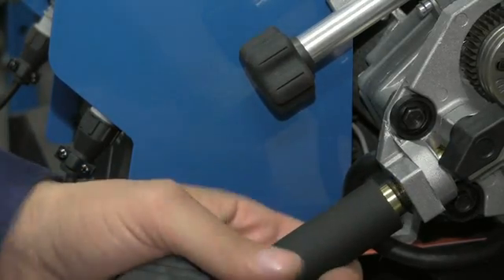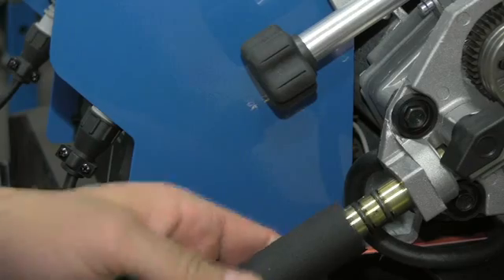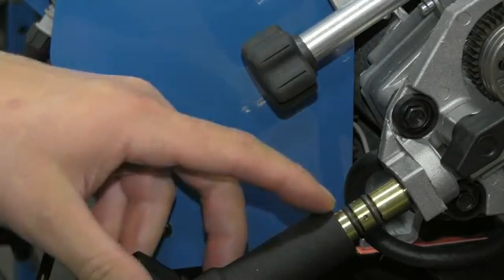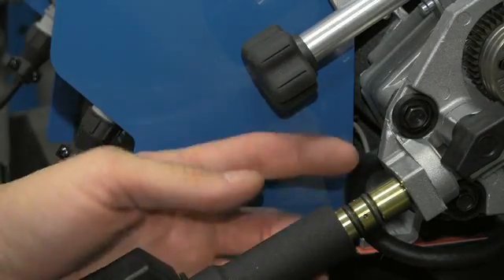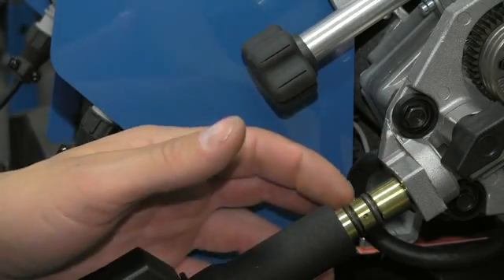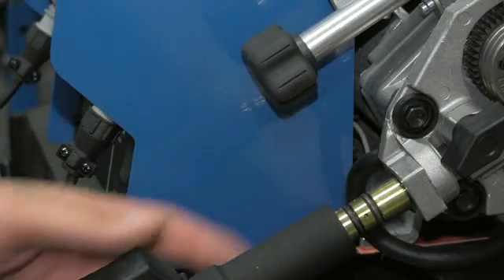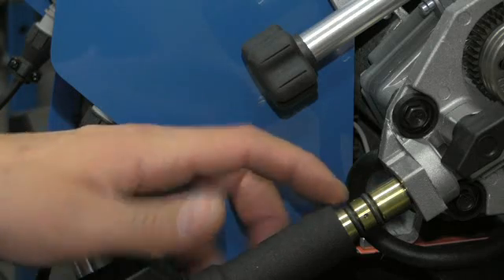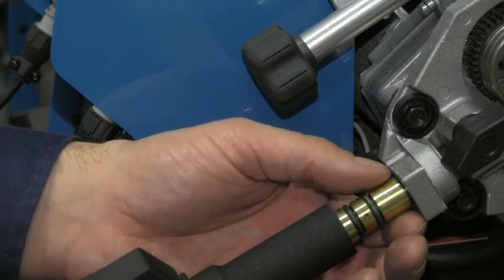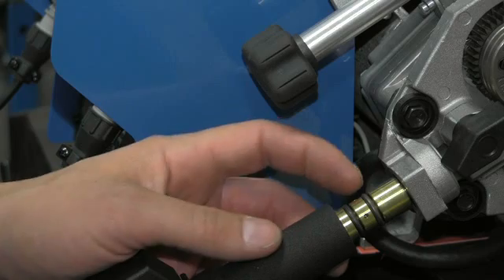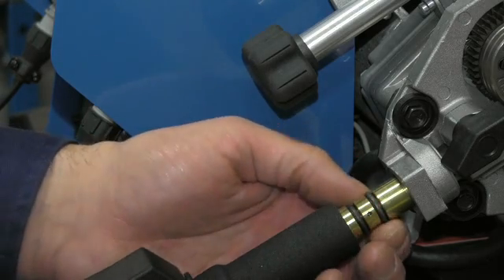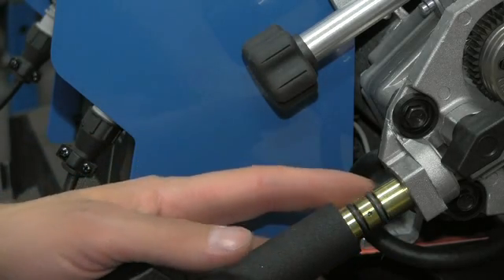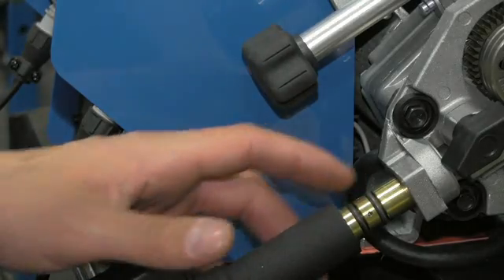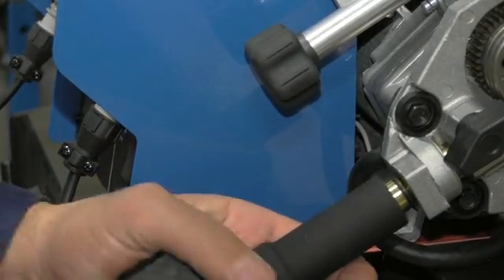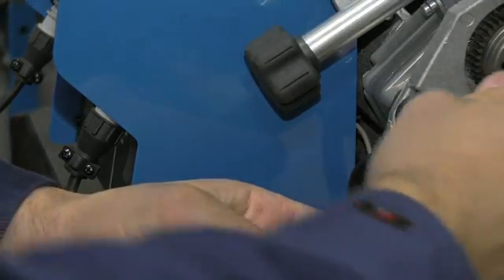So if I go ahead and pull this all the way out, you'll notice the two O-rings right here. These two O-rings seal these holes where the gas comes into the wire drive block to force the gas into the MIG gun. So these O-rings are very critical, that they're completely seated inside the wire drive block, and also that they're actually installed. Sometimes you'll find MIG guns with power pins that have O-rings that are missing or cracked and worn. So these things need to be replaced pretty regularly. This is something that's commonly overlooked. So here I'll seat it all the way in, tighten it down, and then you should be good to go.